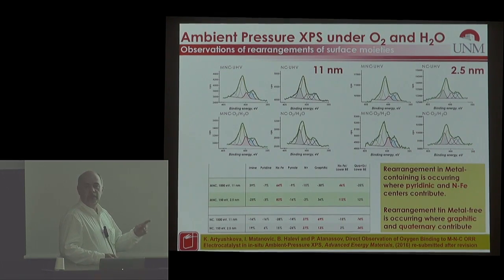So then the next thing is to see whether you can have a direct observation of the oxygen binding to exactly this particular line in the XPS spectra. To do that, you need to have different depths of penetration, thus different incidence energies of the XPS.